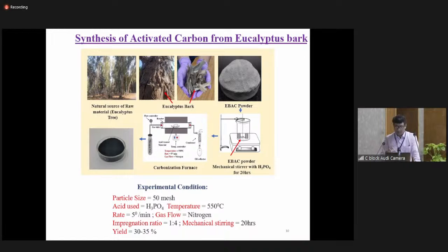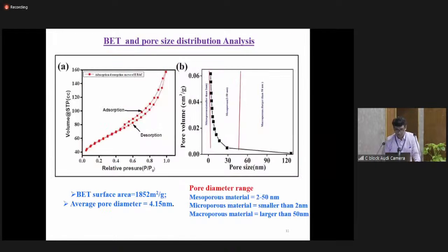And then the impregnation ratio of the biomass to the orthophosphoric acid was 1:4, and that was mechanically stirred for 20 hours. And then we found the yield of that material from biomass to activated carbon was around 30 to 35%. This is showing the photograph of the activated carbon in the petri dish.